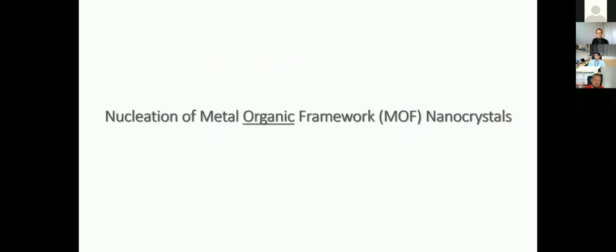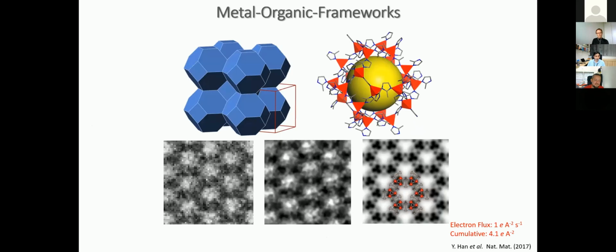Okay, so what is one of the most beam-sensitive materials? It happens to be metal organic frameworks. Even imaging a metal organic framework is not so simple. Here is an image of a MOF, this particular one is ZIF-8, and it was published in 2017. It was imaged under extremely low dose conditions, right? So just being able to image the static structures of MOFs was a very, very big deal very recently, because these materials are beam sensitive.